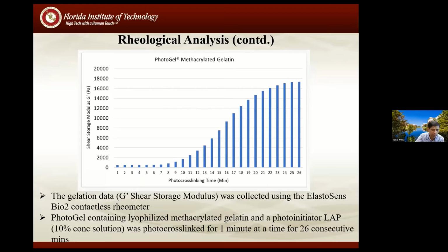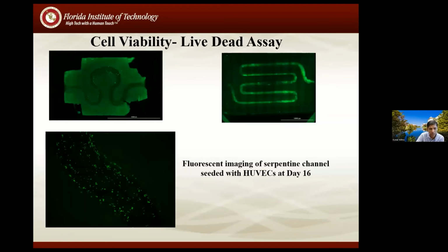We also did some rheological analysis where we look at shear storage modulus versus cross-linking time. As I said, there are many parameters. We just showed you one here, to show how you can optimize this bioprinting process. We are printing some initially simple vascular channels, and we want to make sure that we're able to maintain the viability, because these channels were seeded with HUVEC cells, and even after 16 days, we are able to maintain